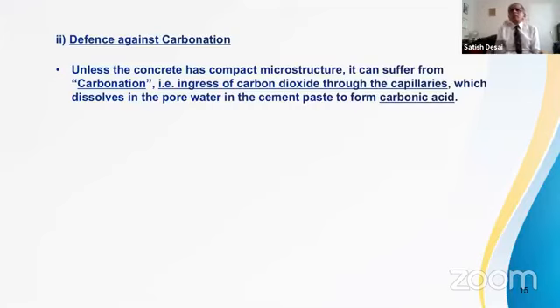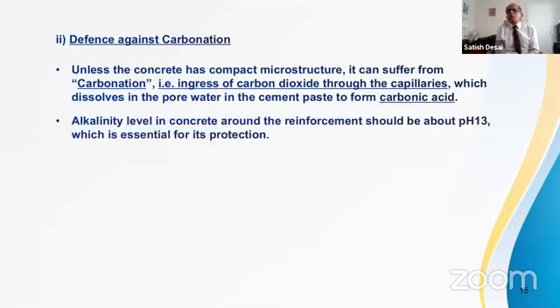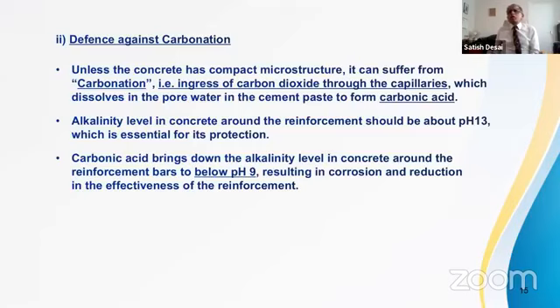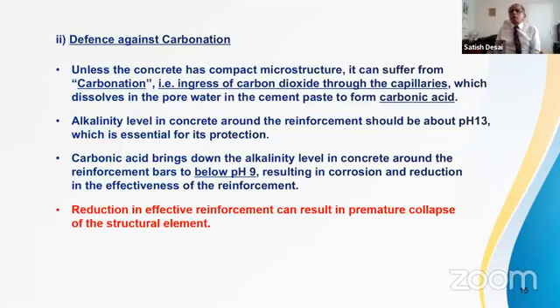Defense against carbonation, ingress of carbon dioxide through the capillaries. This dissolves in the pore water in the cement paste and forms carbonic acid, and that is bad news. Alkalinity level in concrete around the reinforcement should be pH 13, so that the steel is protected. But carbonic acid brings it down to pH 9. What happens is steel gets corroded, its effectiveness is reduced, and effectiveness of the steel reduced means premature collapse of structural element.